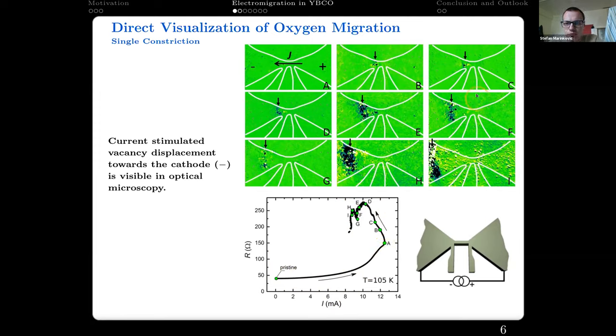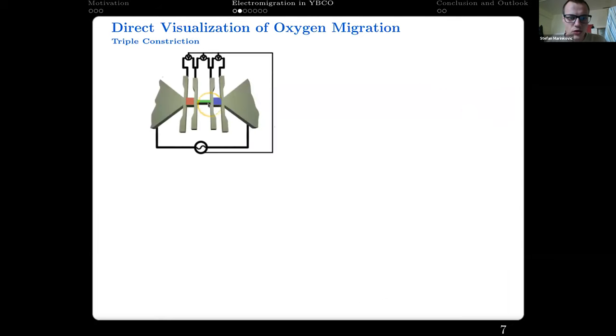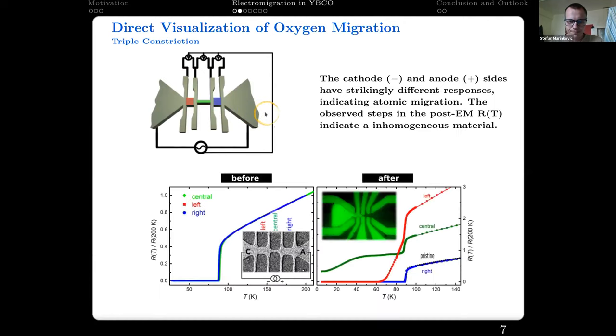Now, this process causes eventual loss of superconductivity in this bridge, but we did not have enough information just from this simple structure. So we redesigned our junctions to have access to both the cathode and the anode side after and before electromigration. So in this spider-like structure, let's say, we performed resistance versus temperature measurements before and after electromigration that are shown on the image below.